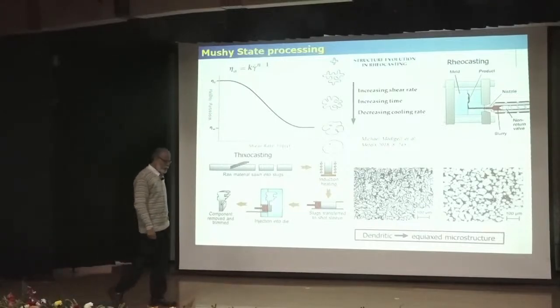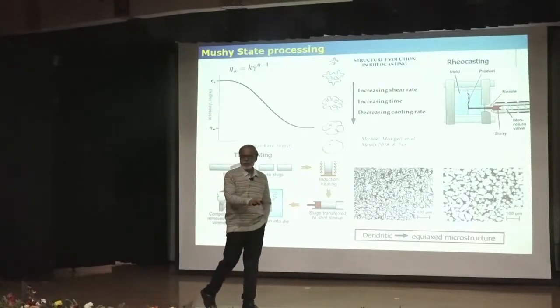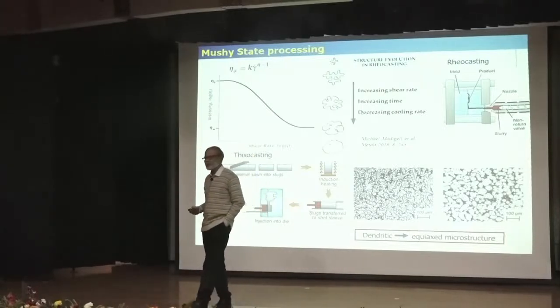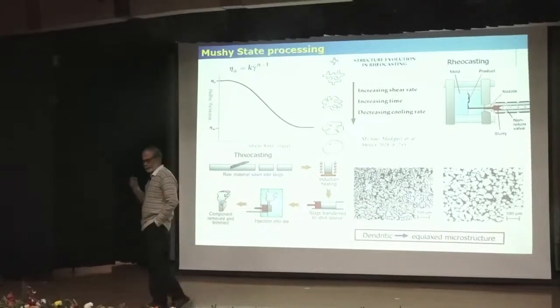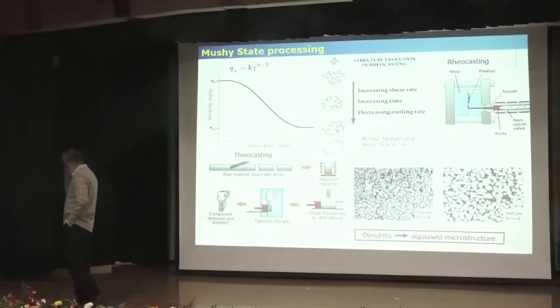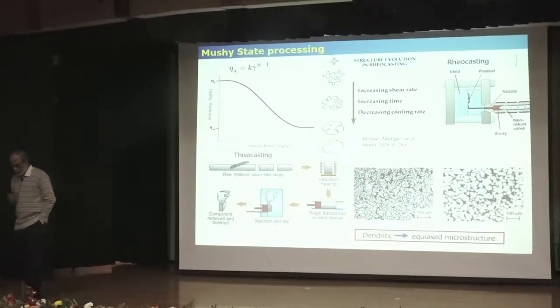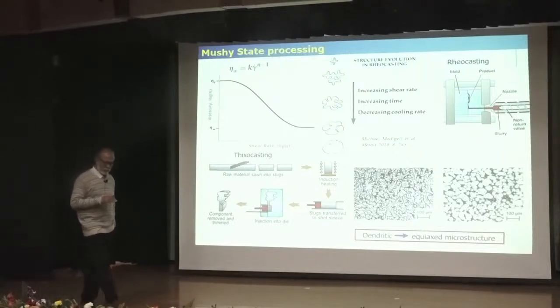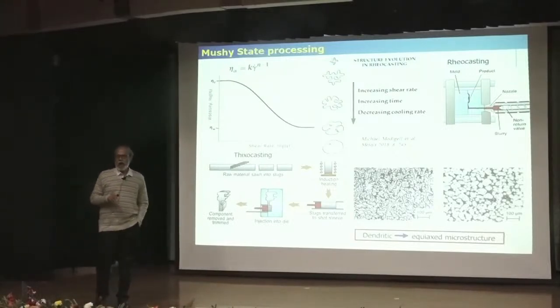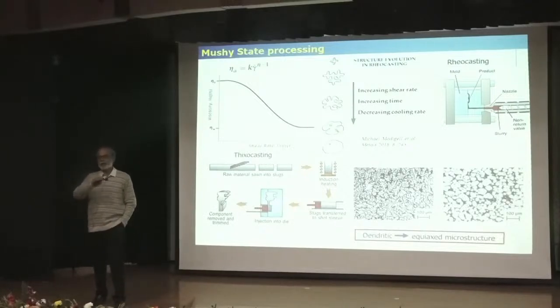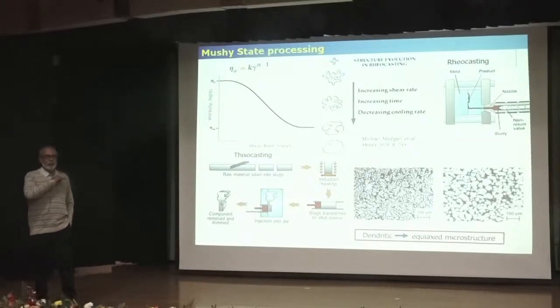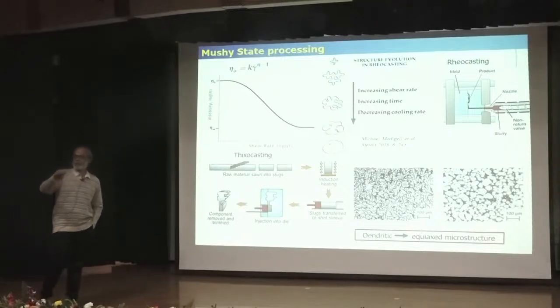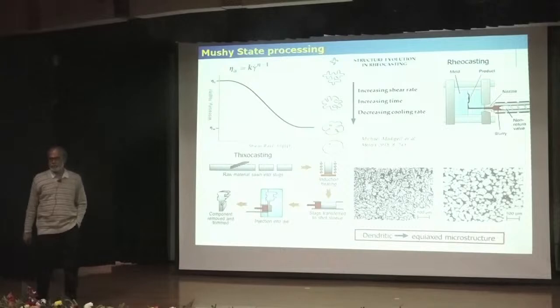And once people understood the happenings in the mushy stage, they were interested in getting rid of that. So Spencer and his group at MIT were conducting some experiments on lead tin alloy to reduce the solidification stress. And they found that when they apply, it is sometime around 1970, when they apply shear stress, the solidification stress reduces.